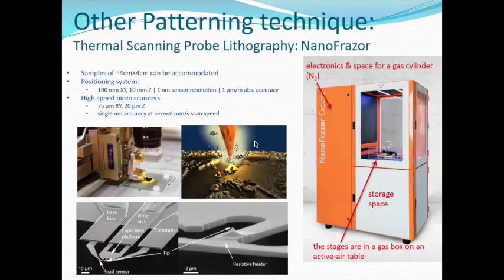The most recent one is another new one, thermal scanning probe lithography, a tool we call the NanoFrazor. Instead of a UV lamp, laser, or e-beam, it actually uses a heated scanning probe. The probe is in contact with one type of polymer called PPA, and it burns the polymer, making it decompose and evaporate, which makes nanometer-range structures like this one showing. The structure here has the reading path and the writing path. So basically, you heat this tip to burn the polymer.